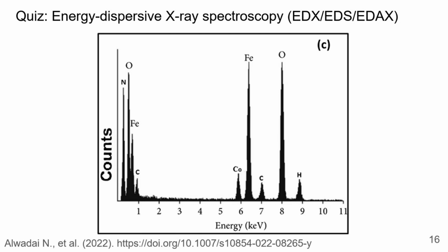But since I'm not there in person, I'll just let you appreciate the spectrum for a second. Realize that this would appear entirely plausible if you weren't looking that hard or weren't familiar with EDX, but there are issues with it that are immediately recognizable. First off, hydrogen will never, ever show up on an EDX spectrum. It is too light an element to actually produce characteristic X-rays. So right off the bat, if you see hydrogen on an EDX spectrum, something has gone terribly wrong.